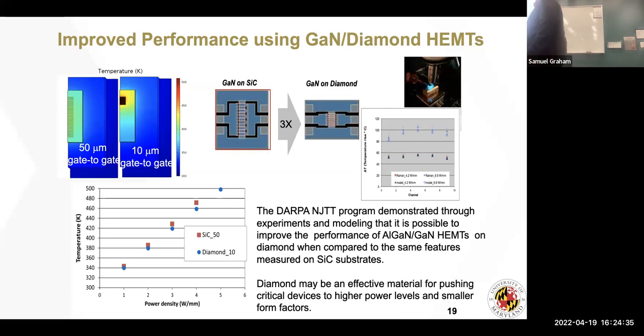So the other part is I mentioned, well, what about going to diamond? So we've done this work through the DARPA Near Junction Thermal Transport Program. This is a very interesting program where we showed that we could take gallium nitride or silicon carbide, shrink it down by a factor of 3 by putting on diamond, and you don't get a penalty in terms of temperature rise. So that's actually good. I can make these devices smaller, more compact, in more intense heat sources, and I can still dissipate the energy.